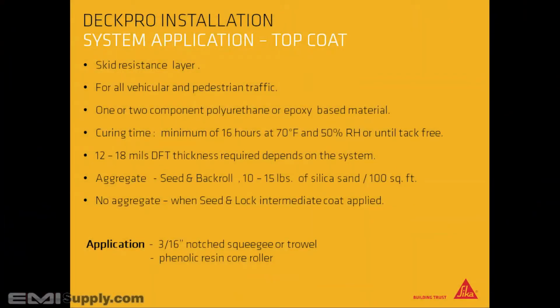Top coat. This is the skid resistance layer for vehicular and pedestrian traffic. 1 or 2 component polyurethane or epoxy-based material. Curing time, minimum 16 hours at 70 degrees Fahrenheit and 50% relative humidity, or until tack-free. 12 to 18 mils DFT thickness is required depending on the system.